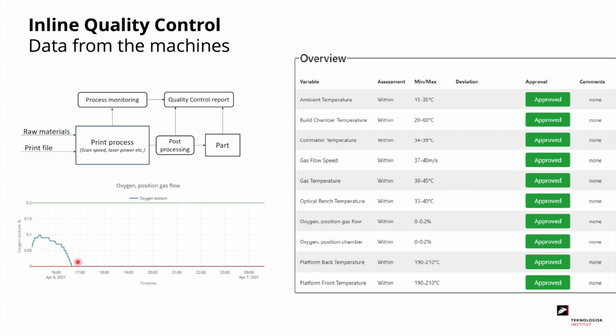On the lower left you see a graph of the oxygen, and you can see that the oxygen during the build job has never been above 0.1. This will mean that this build job is approved and there are no red flags for this.